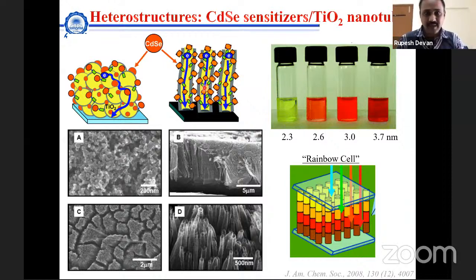But after that, what people did was create these CdSe quantum dots with different particle sizes, from 2 to 4 nanometers, and put them in a rainbow cell. So what happened here is the 4 nanometer particles were at the bottom, and then they started decreasing the particle size, and started coating different particles up to the top. So that really helped the absorption of a large number of reflected lights, and that created a very good efficiency out of the solar cell.